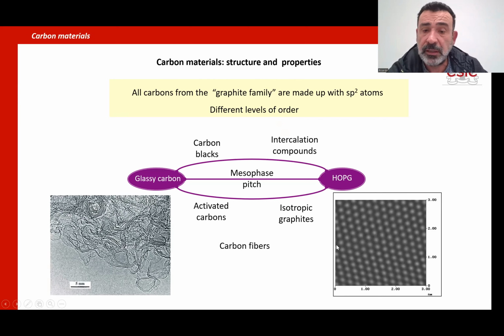But if you go to the other border, to the classic carbon, you can see the layers. You can see by high resolution transmission electron microscopy the layers, but they are not perfectly aligned. They are twisted. They have many defects. You have only 4 or 5 layers on top of the other, or just one or just two.